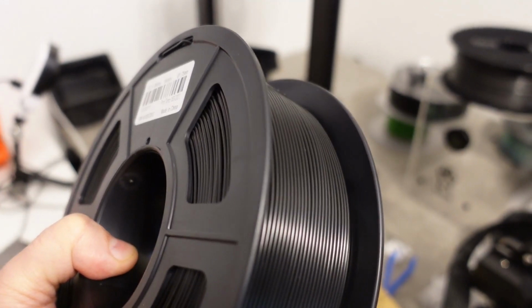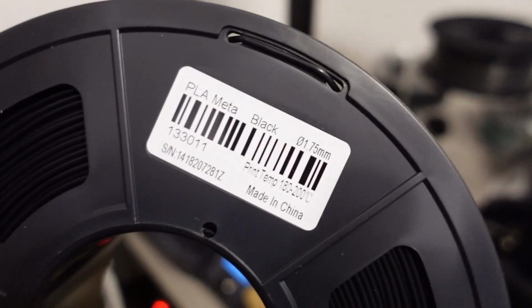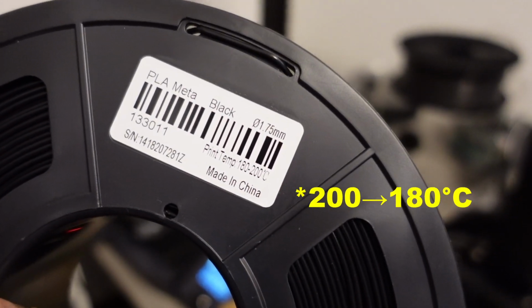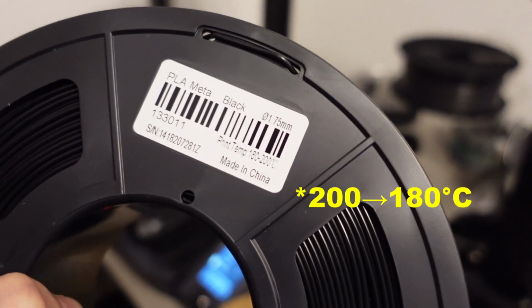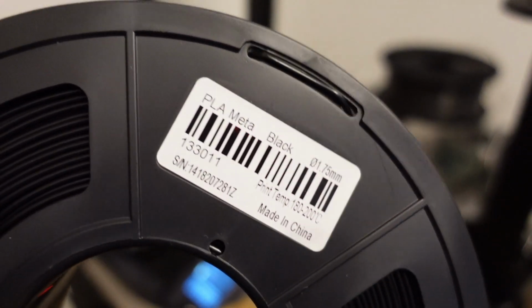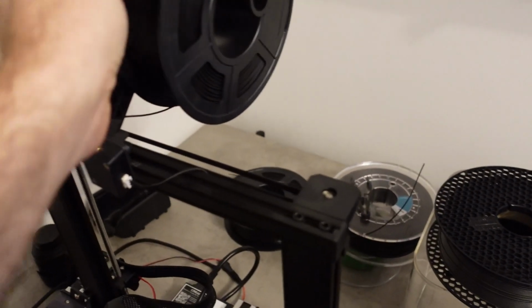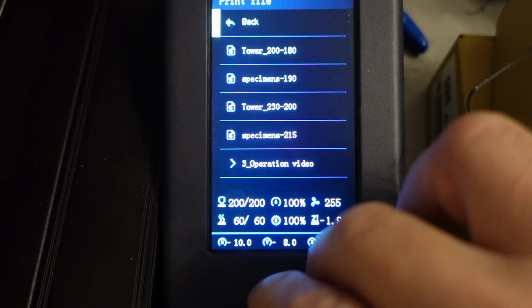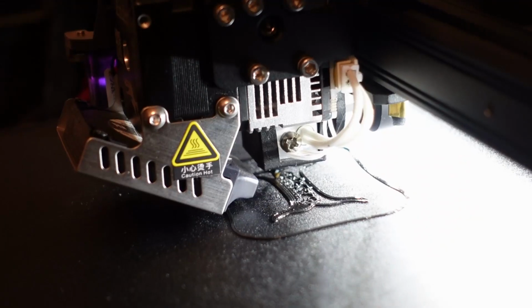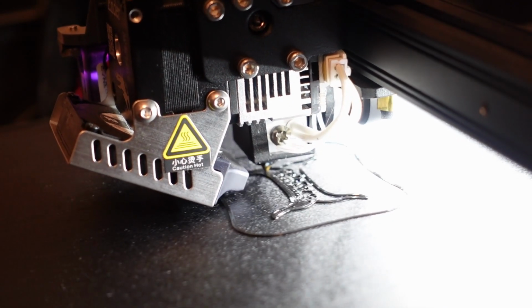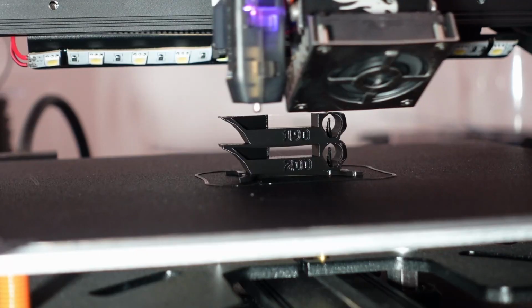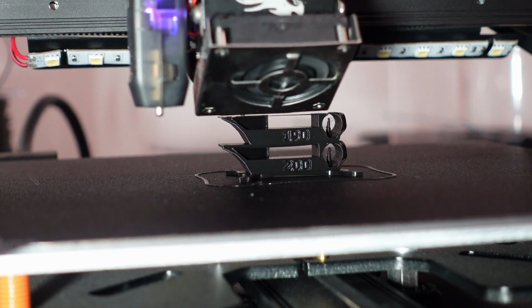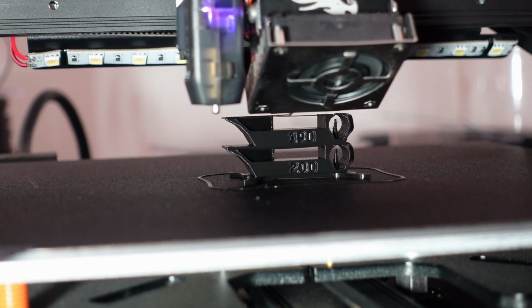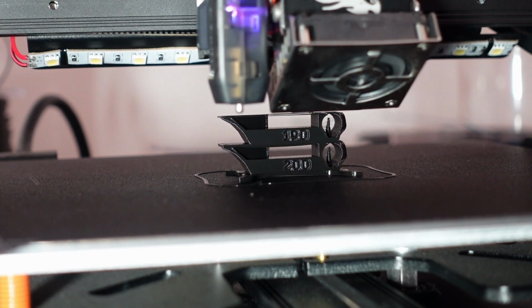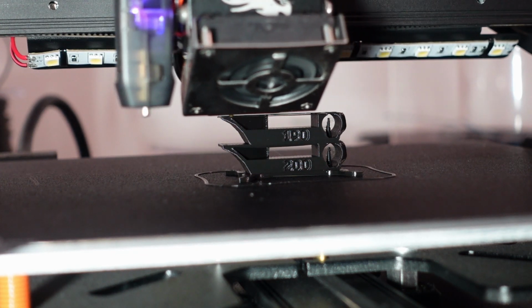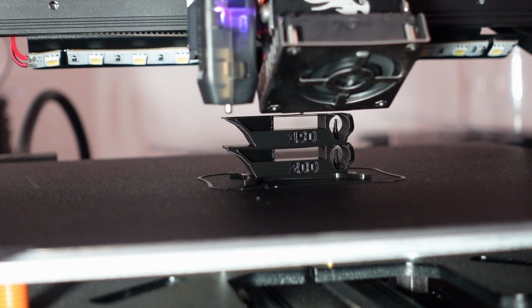And now moving to PLA META because it is also in black color, and the temperature tower will be from 200 down to 180 degrees Celsius. I usually never print on so low temperatures. The first layer is okay. This is the bridging on the second element. And it's okay, there is no stringing at all and the bridging is perfect.